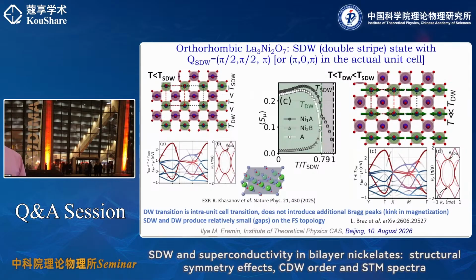Now, on the localized picture, I saw mostly people did calculations in the tetragonal phase. What I think is missing is to do the calculation for the orthorhombic phase, to show that you can consistently get the pi over 2 phase, and then you change the lattice constant and take your theory and consistently get the superconducting state to be dominant. Because what I saw mostly is always a play with the tetragonal phase. People change filling, say this is a mode-selective transition, and so on and so forth. It's all very nice, but there is no experimental reference point. In my opinion, there are two experimental reference points: bulk crystal at ambient pressure, because there is no ambiguity about the parameters, and thin films, which are known to be superconducting. So take these two reference points and consistently explain them within your strong coupling theory, and then everything's fine.